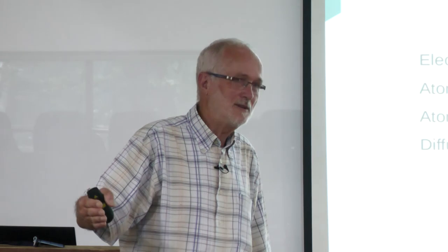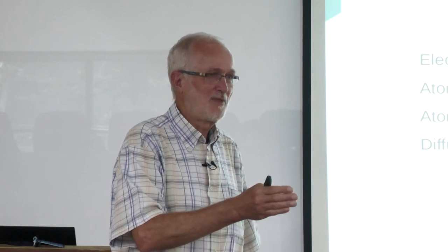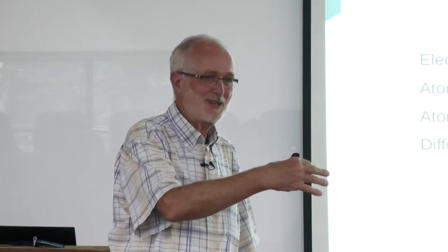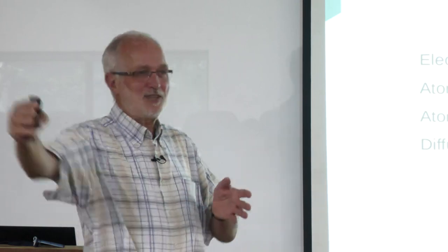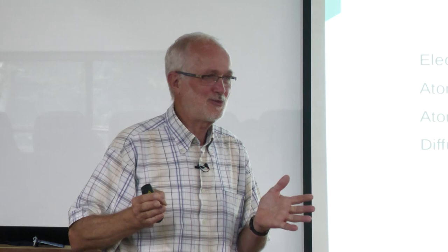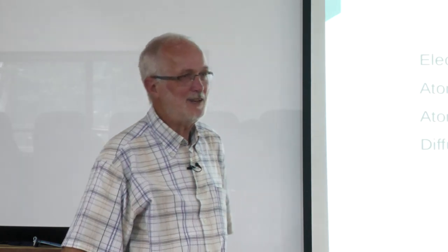This is important because this means that on a time scale longer than many seconds, carbon tends to diffuse somewhere. And this can also be measured. It goes to dislocations, segregates at dislocations. And then if we deform, these dislocations have to leave this cloud of carbon atoms. This gives the upper yield point, which you observe experimentally. So that's the motion of atoms here.